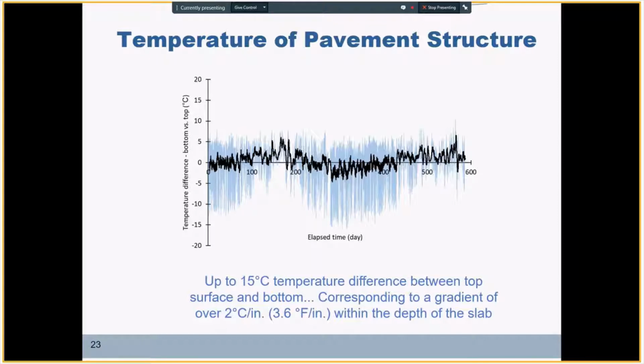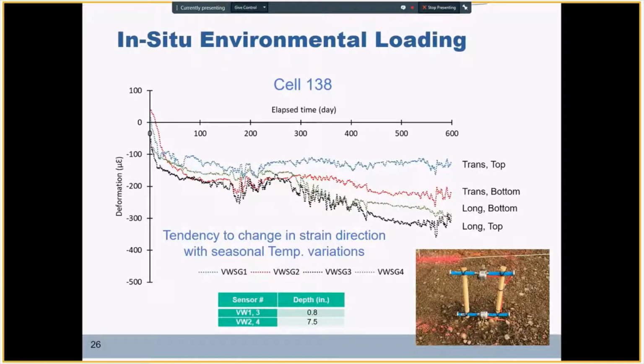The vibrating wire gauges also record in-situ strain caused by environmental effects. Here I have data from cell 138 - these are isothermal measurements, containing only deformations caused by shrinkage, warping, and curling. There is a tendency to change in strain magnitude and direction with seasonal temperature variations, but overall deformations reach strain values as high as 300 microstrains, with the maximum observed at the surface for sensors aligned parallel to the direction of traffic.